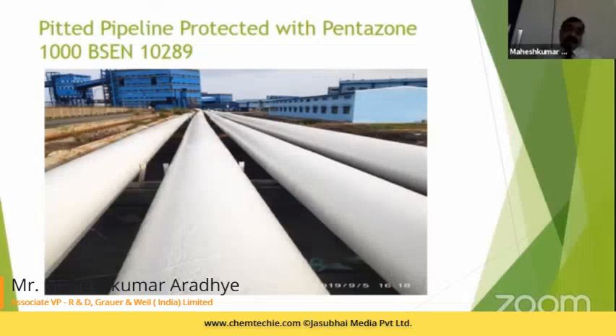onto the pitted surface also. This pipeline is from NTEPCL at Chennai, and it was coated with our Pentazone 1000 BS EN 10289. It was coated in the year 2018, and very recently a corrosion audit was carried out by me, and we found each and every pipeline is 100% intact. The atmospheric condition here is CX, that is more than C5M, CX, C extreme as per ISO 12944 Part 2 environmental classification, and it is performing very, very well in this area.